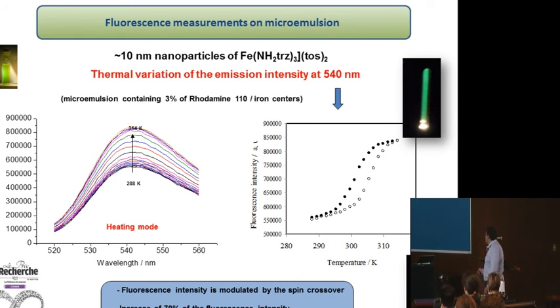This means that we can detect single objects using this kind of strategy. Remember, for the 4 nanometer particles, you have a transition but no hysteresis. Now for the 10 nanometer particles, we have again the hysteresis. So between 4 nanometers and 10 nanometers, you really have a decrease of the cooperativity.